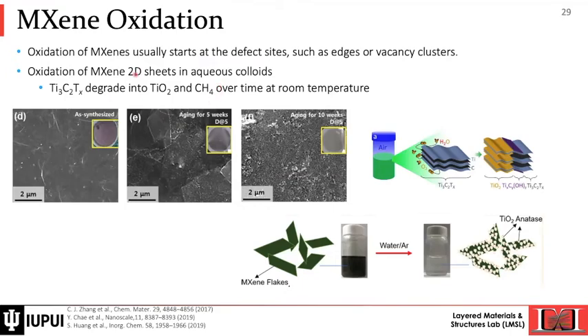And this is really the result of the great work of Professor Vadim Mochalin of Missouri Science and Technology, that he explained how this phase transformation happens. And here we show basically an as-synthesized MXene film, and after aging of 5 weeks in water in a refrigerator at 5 degrees Celsius and 10 weeks. And you can see after 5 to 10 weeks, almost everything turns to TiO2.